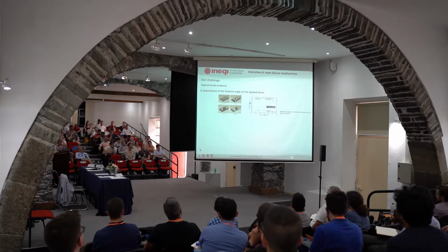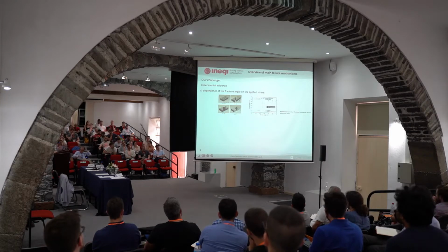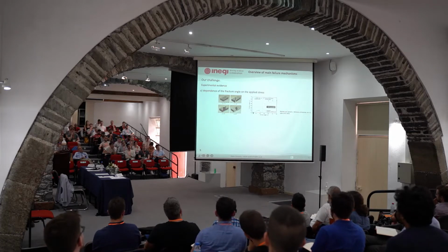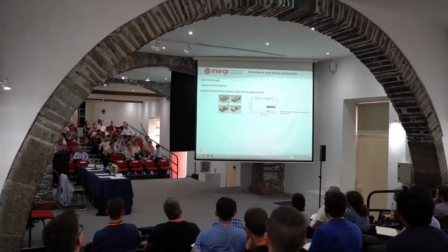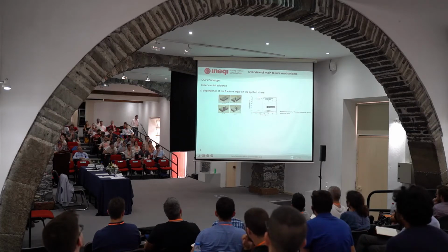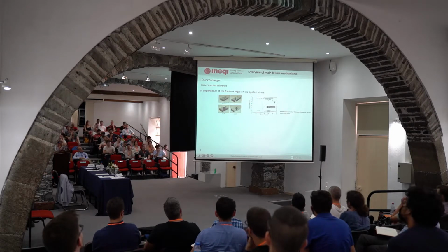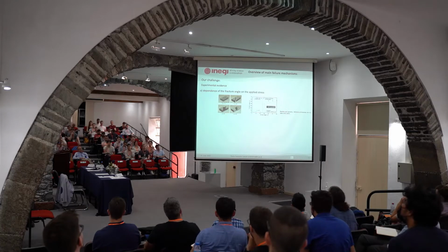So what we can do here is that we use a high-speed camera to identify the fracture angle. So we're looking at the side of the specimen and we are able to capture the fracture angle. And you can see now if you relate the off-axis angle, from 15 all the way to 90, with the fracture angle, as we have different combinations between the compressive transverse stress and in-plane shear stress, we get different angles. This is important because if we want to simulate how a crack propagates, you need to know the orientation of the crack in the first place. So this is something that we need to get as baseline information if you want to then use, say, a continuum damage model. Okay.